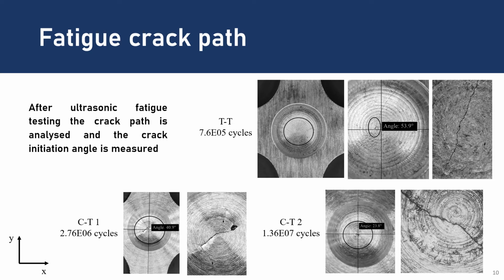Both TT and CT specimens presented crack initiation at the specimen center, the fatigue testing region, and from that the crack path was analyzed as well as the crack initiation angle. The crack initiation angle was measured from the x-axis, as here presented. In this case, the axis comes here and the crack initiation begins with an angle.